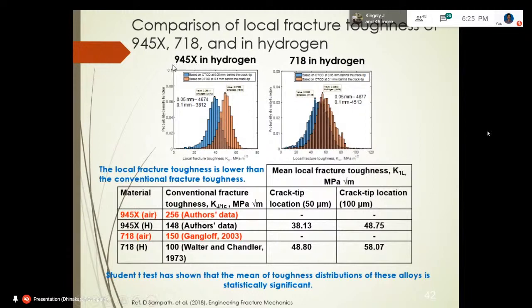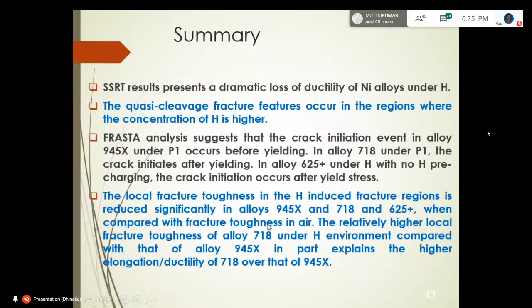But we need to remember the 945X is specially made for oil and gas purposes. But the thing is, they tried to fix one problem by eliminating grain boundary precipitation, but the failure mechanism is completely different. It was mostly cleavage and twin boundary cracking. So that's the problem with hydrogen embrittlement. There are several combinations of mechanisms operating simultaneously. We need to carefully strike a balance to get a better alloy.